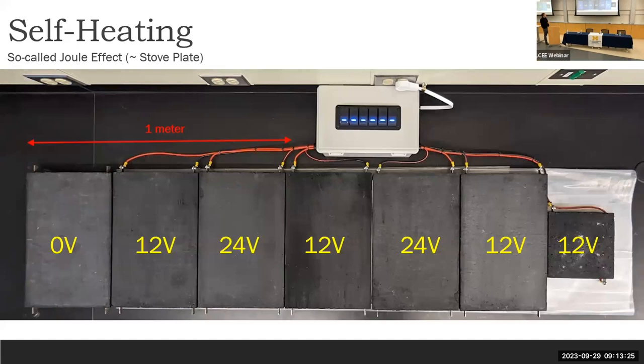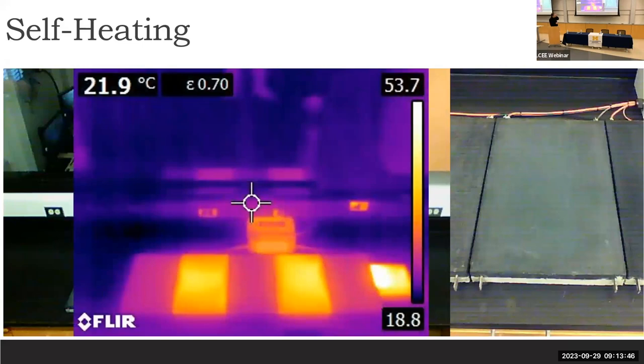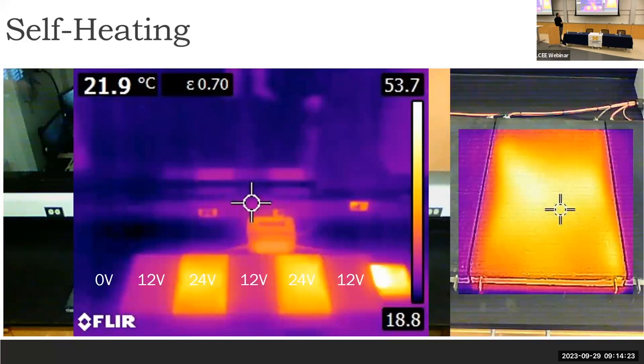These are some lab examples for sidewalks in tile format, where we connect them here to 0 volt, 12 volt, 24 volt, 12 volt, just to see how that operates. The system is highly repetitive. And when you look at the temperature rise, you see how homogeneous the temperature rise actually occurs in the system. So if you want to get rid of the shovel or the salt on your roads, here's concrete for self-heating applications. All you need to do is connect it to a voltage source, positive, negative charge. And by controlling the voltage, you control the temperature with high accuracy, scaling with voltage to the power 2. And you see how homogeneous that is.